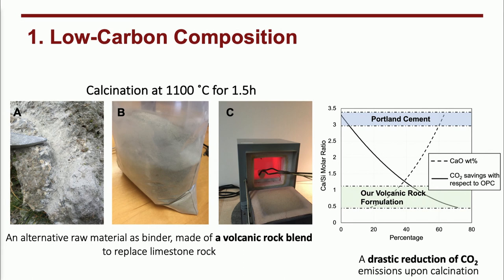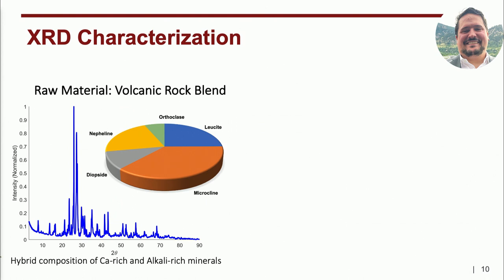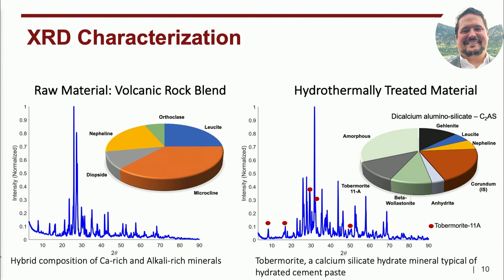With respect to Portland cement, we can have a reduction of CO2 that, depending on the calcium-silicon ratio, goes from 50% to 70%. We still need to calcine these rocks just to transform the minerals into oxides. So calcination is still required. Once the calcined material is created, the material is exposed to hydrothermal synthesis.